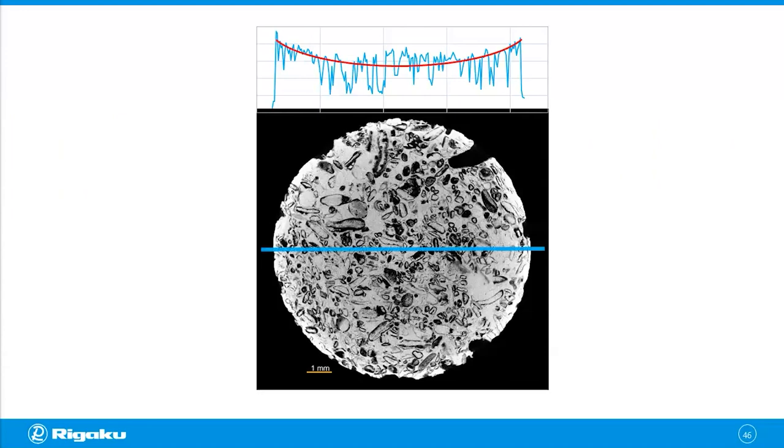Now let's try simple thresholding. If you set one threshold, your segmentation of the solid part would look like this. Let's zoom in a little bit. So you're setting, for example, the threshold so that those voids are not painted red. But at the same time, you have a problem towards the center where you see all those gray holes. They are not painted red, although they should be.